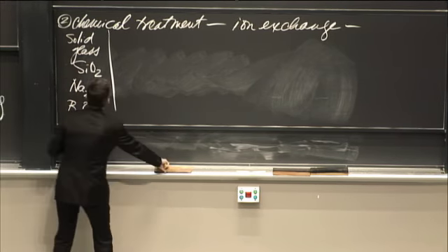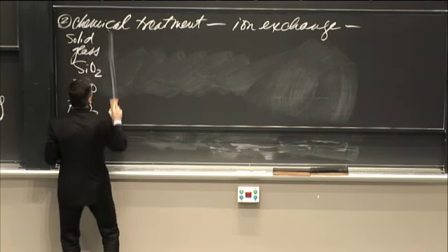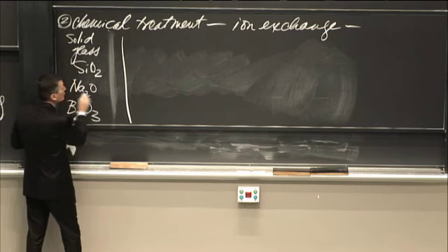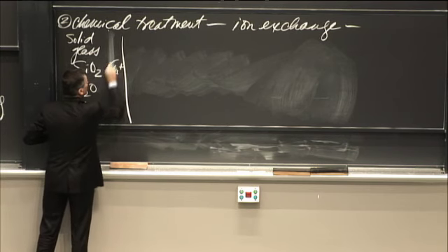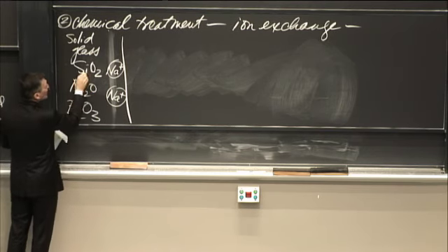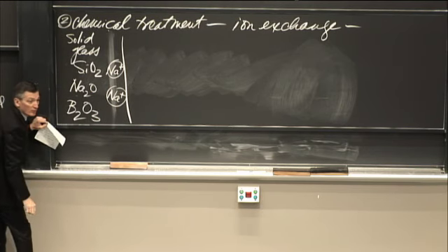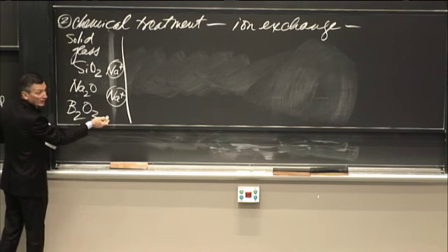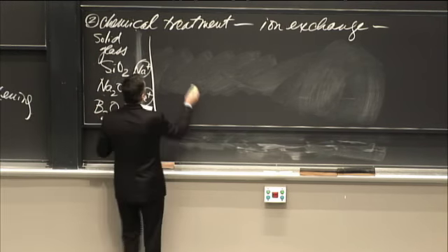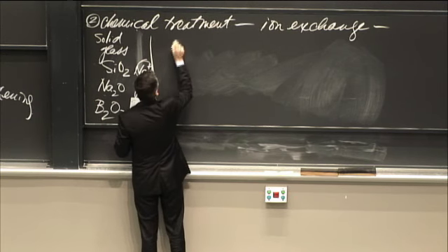And just to put a little skin on the bones here, I want to show what the sodium oxide actually looks like. Sodium oxide goes in as sodium cations and oxide anions. The oxide anions go in and they break some of the silica chains. But the sodiums don't get involved in that. They just sit around as spectators. All right?